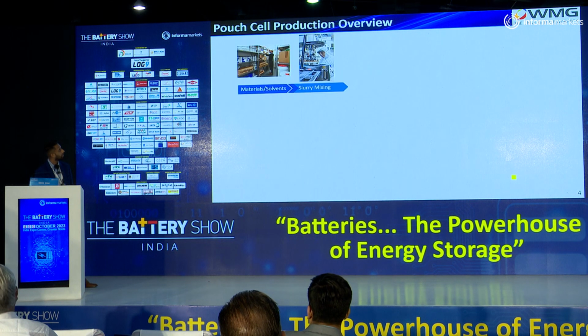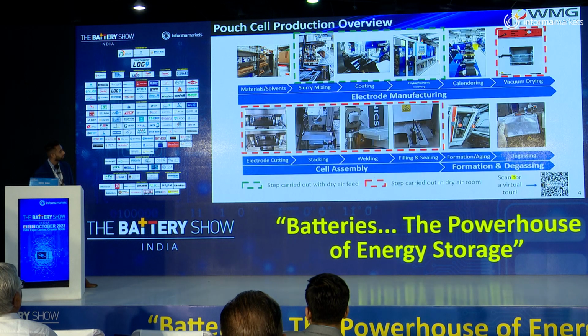So what do we actually have at our facilities? So a quick overview. Why Warwick is so well placed is that we have key control through all of these activities. So we can go from the material solvent all the way to the slurry mixing, the coating, the drying, calendaring, the cutting, the stacking, the welding, the filling, the sealing, and the formation and aging.